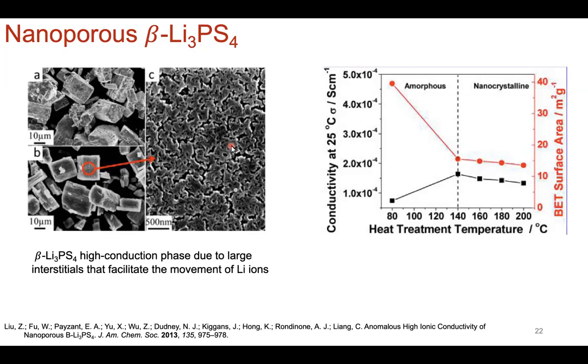So if you were just to take lithium sulfide and P2S5 and combine it in the solid state, heat it up to some temperature and then cool it down, in the bulk phase you would get the gamma phase. But you can access this high temperature phase by doing a liquid phase synthesis in tetrahydrofuran at much lower temperatures. So basically just stir the precursors in tetrahydrofuran for a day or two, or some long period of time. And then you dry off the THF.